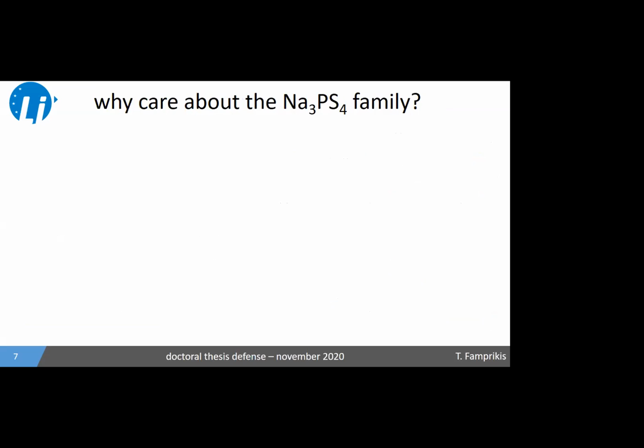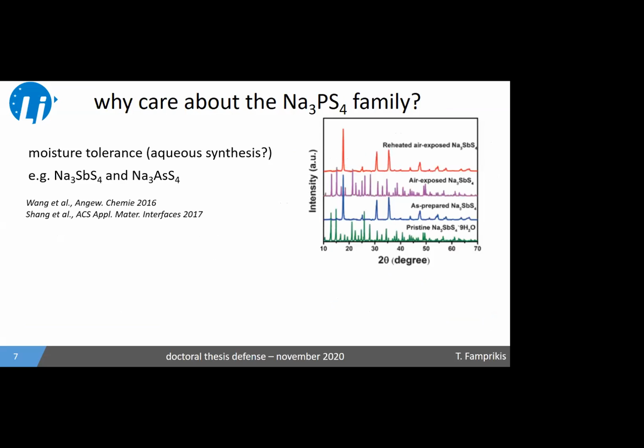So why do we care about this Na3PS4 family of materials? I will highlight here what I think are the two key advantages. One is a distinct moisture tolerance of these materials, which is not a given if you compare it to other solid electrolytes which decompose in contact with air or water. And this is also, I think, very interesting from an upscaling point of view, because we can then envision an aqueous synthesis that would be readily scalable and cheap. I show here, for example, Na3SbS4, which simply forms a hydrate when exposed to air and can simply be dehydrated by heating it up. So it does not decompose in contact with moisture.